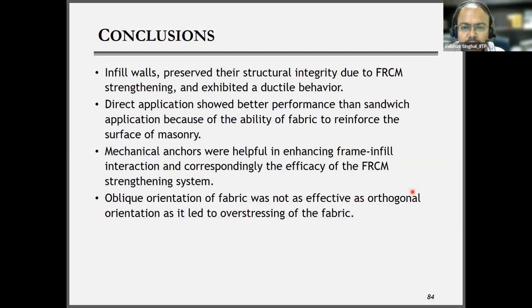So finally, what we have found out from these tests of masonry infill in RC frame is that if you apply this strengthening technique, definitely your frame with masonry infill will provide a better response. It will maintain the structural integrity and better ductile behavior. Direct application, we have seen, has shown better performance compared to the sandwich one. And of course, the mechanical anchors are helpful. Mechanical anchors avoid the early separation of the wall from the frame, and improve the efficiency of the FRCM.